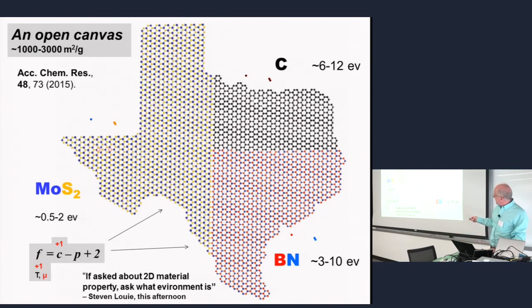This slide, actually, I don't discuss it, but it just emphasizes one important general feature. We call it, in one article, open canvas. Two-dimensional materials are different in a simple but fundamental way from 3D crystals, in that they are fully open surface, right? Which means that exchange with environment, with atmosphere, is almost immediate in principle. As opposed to bulk crystal, if you change thermodynamic conditions around bulk crystal, atoms have to diffuse in and out. It's a very slow process. You have to anneal it for a long time. In this case, in principle, it's very fast.